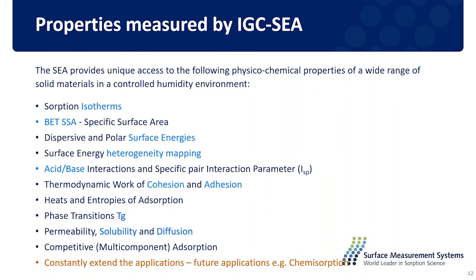And by choosing different kinds of probe molecules, both nonpolar and polar solvents, we can get different components of the surface energy of the solid material, from the dispersive part as well as the specific or the polar part. And of course, we are injecting the probe molecule at a series of different concentrations. We can also get the high energy sites as well as the low energy sites on the surface, giving a heterogeneity mapping of the surface in terms of surface energy. And by injecting different polar solvents, we can also investigate the acid-base property of the surface. Is it more electron donating group on the surface, or are there more electron accepting groups on the surface?